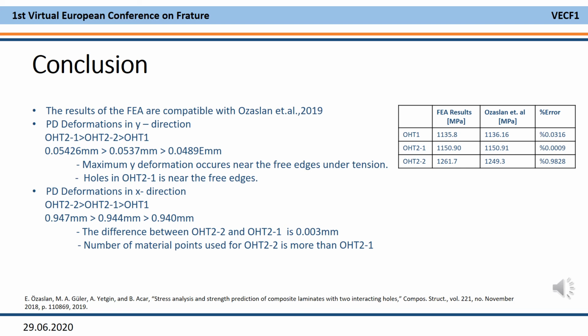For peridynamic deformation in y direction, the maximum deformation occurs in the specimen with hole distance 3 times the diameter. The reason is that normally maximum y deformation occurs near the free edge under tension, and the holes in this case are near the free edge.